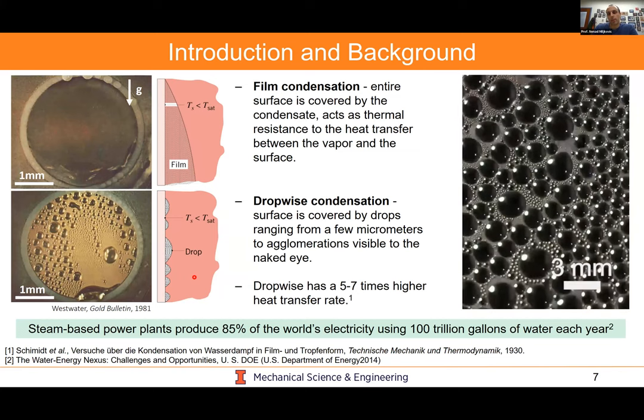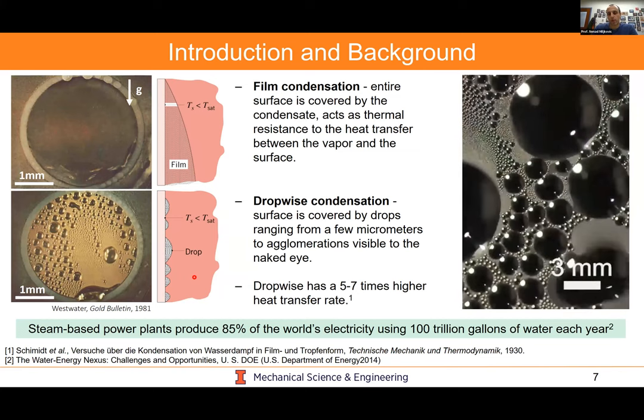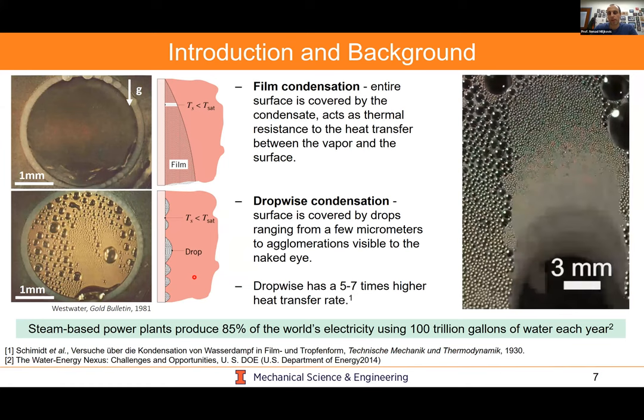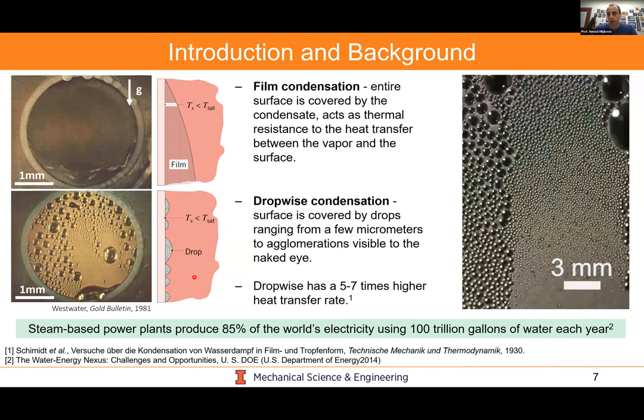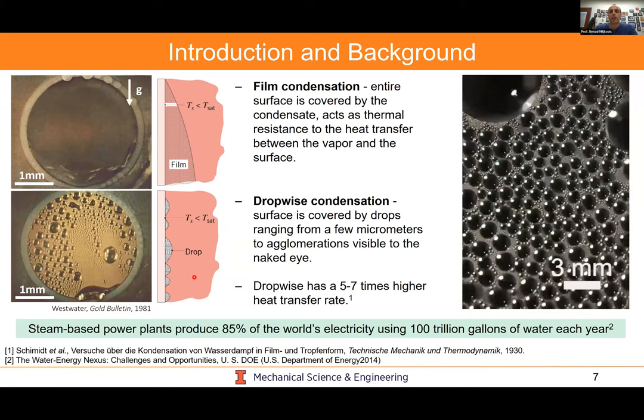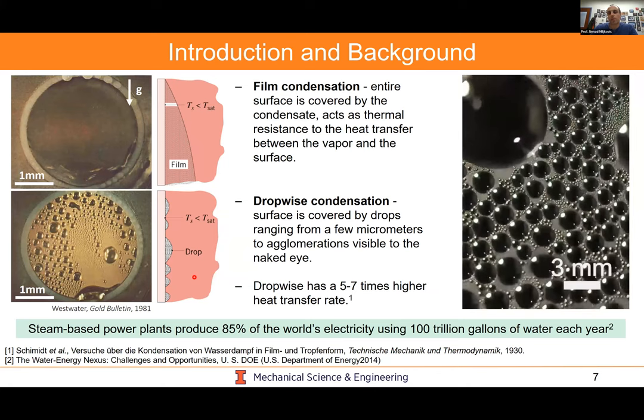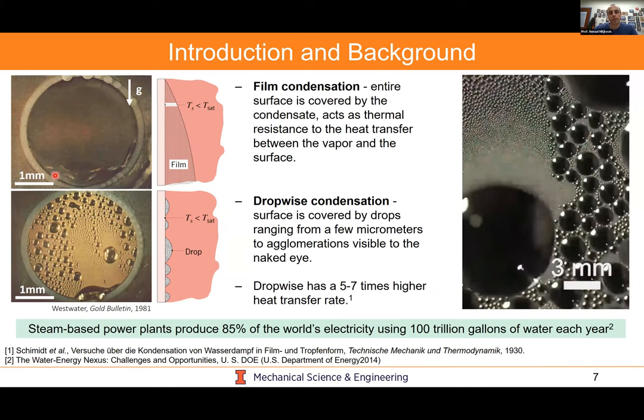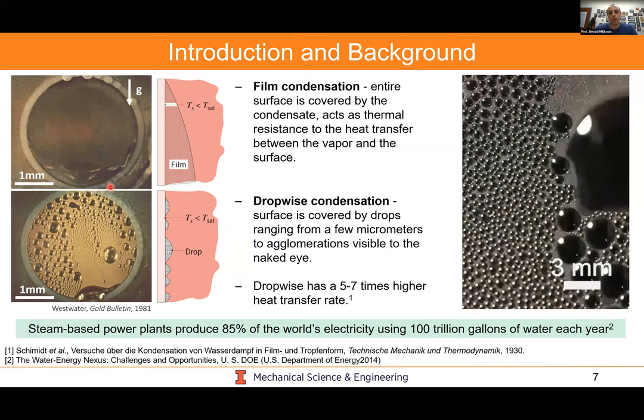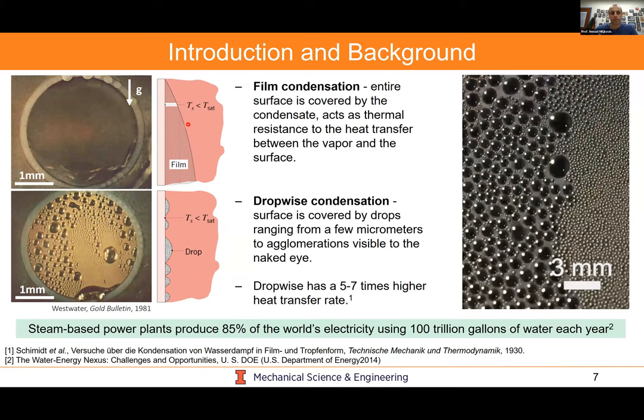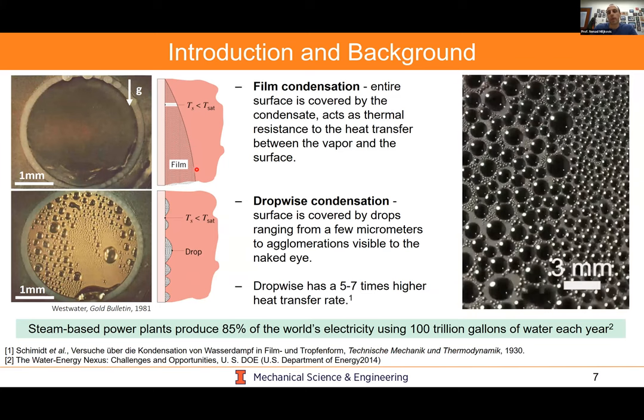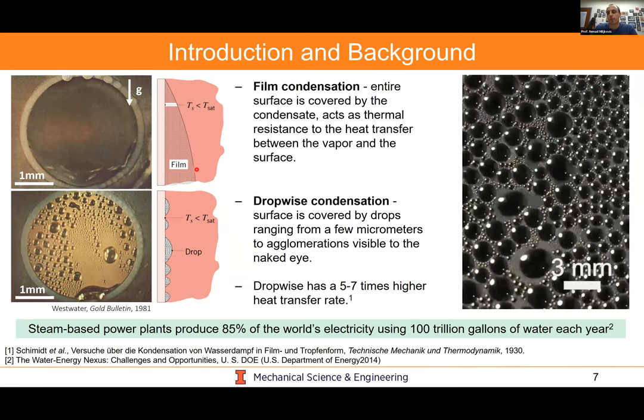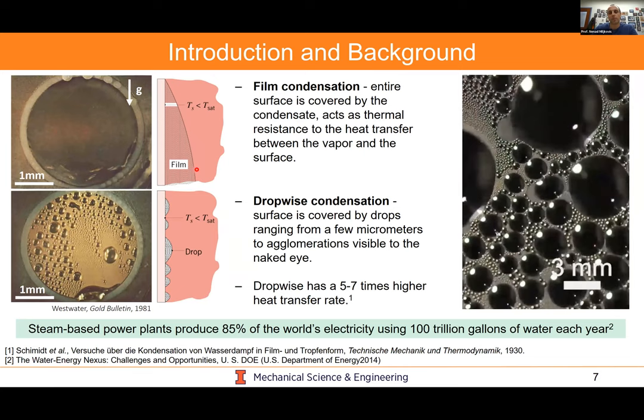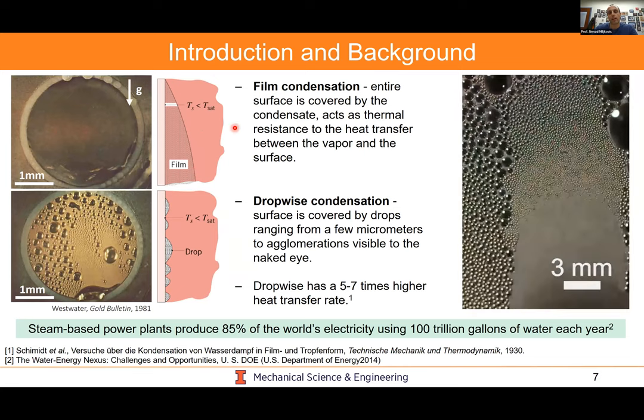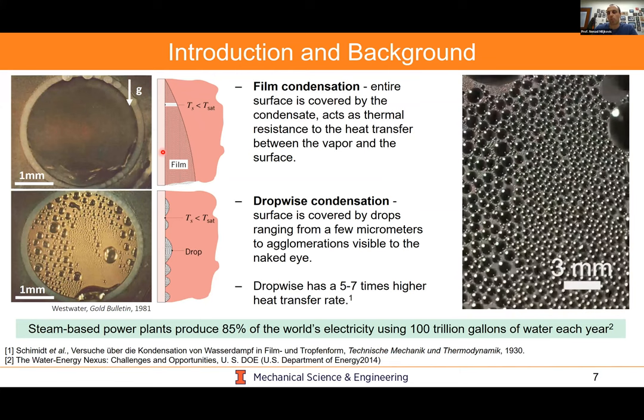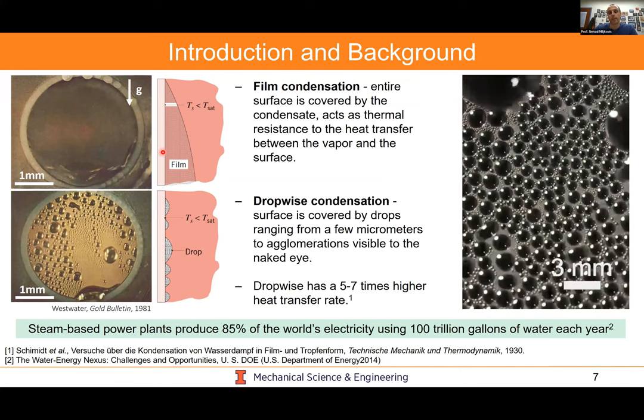Typically, this condenser is just a bare metallic tube. It could be copper, nickel, it could be steel, it could be stainless steel, depending on where you are around the world. But what ends up happening is this condensation process tends to form a very thin liquid film, as you're seeing here in the top left image. This liquid film basically inundates the surface and it causes a barrier to heat transfer, which reduces the efficiency of the heat transfer from the steam side to the coolant side, where typically you have multiple tubes with coolant water flowing on the inside.